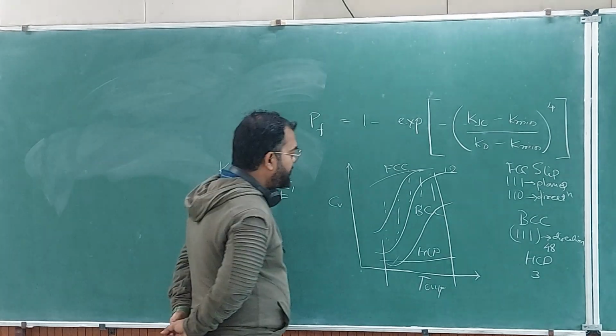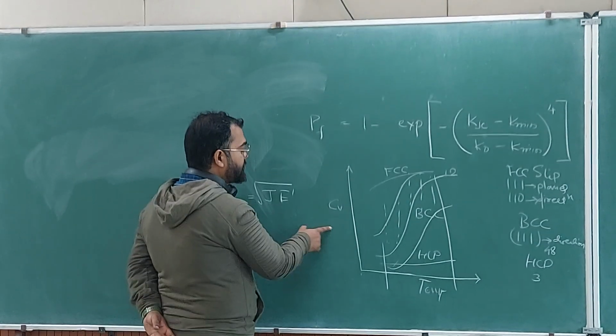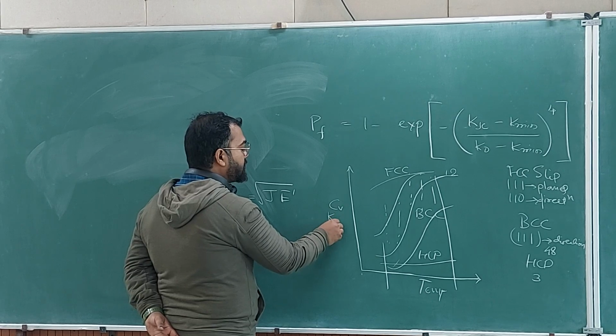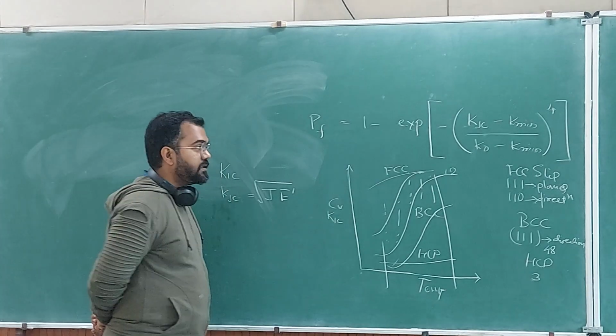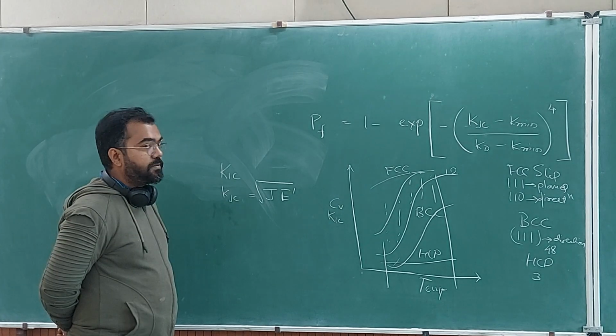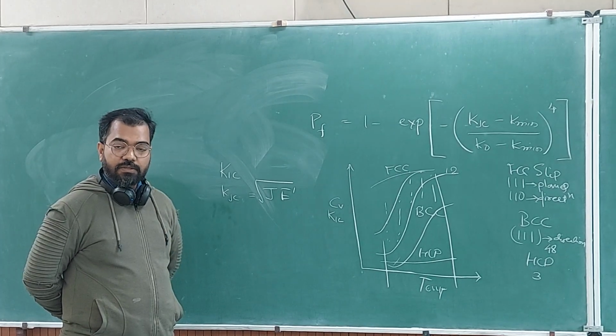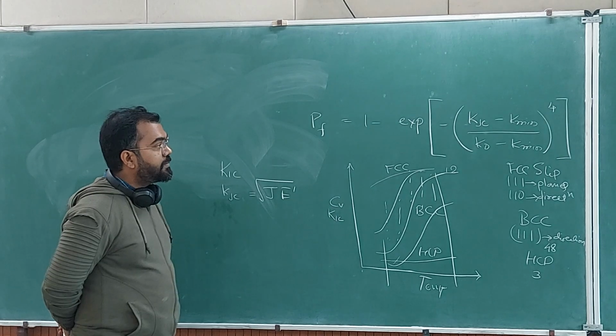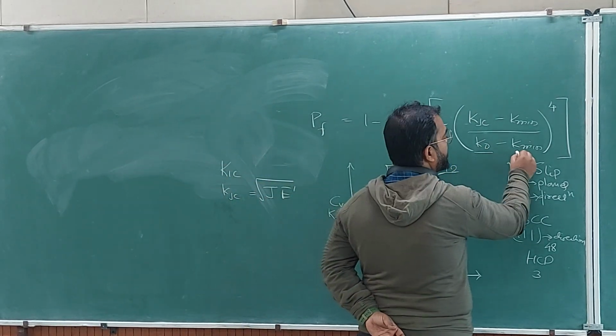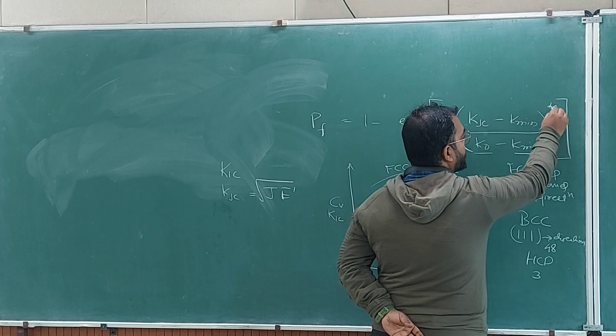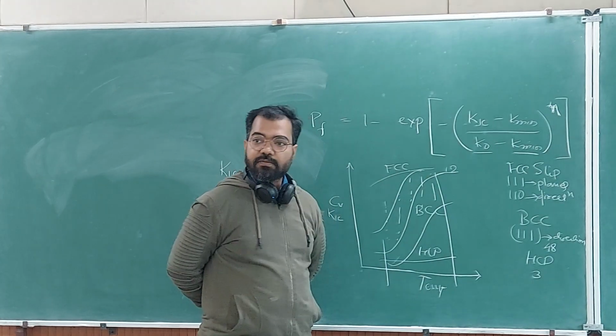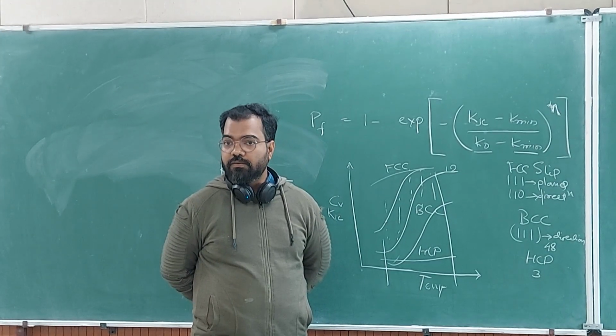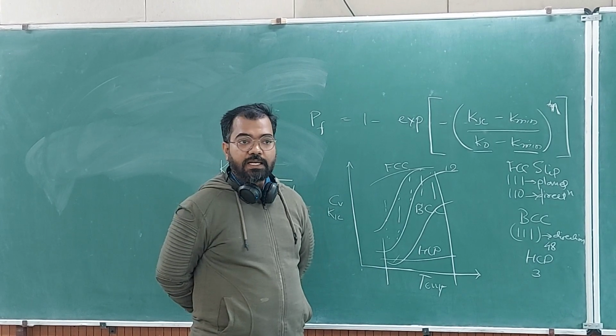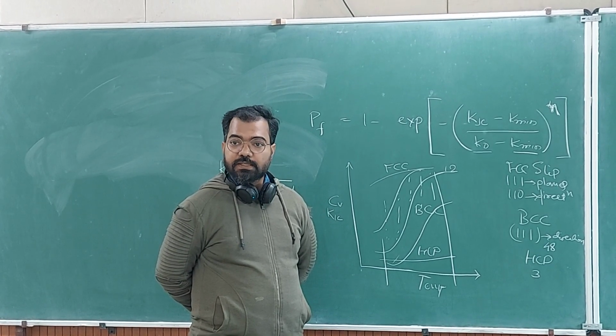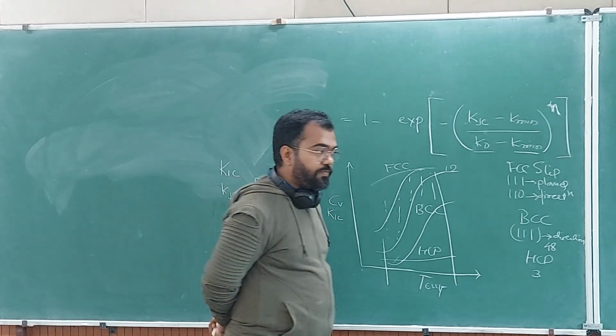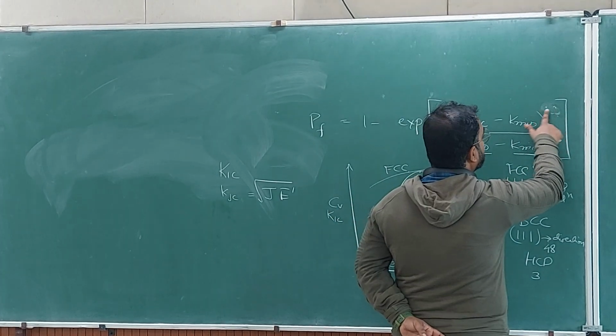So with this, when you plot K instead of Charpy energy, you will also see the kind of scatter that we discussed, following Weibull's three-parameter distribution. What are the three parameters here? One parameter is K naught, another is K min, and the third is this N, which Weibull decided. That value we found to be 4 because it scales with the active plastic volume, which scales with B into K to the power 4. So N is 4, that is solved.